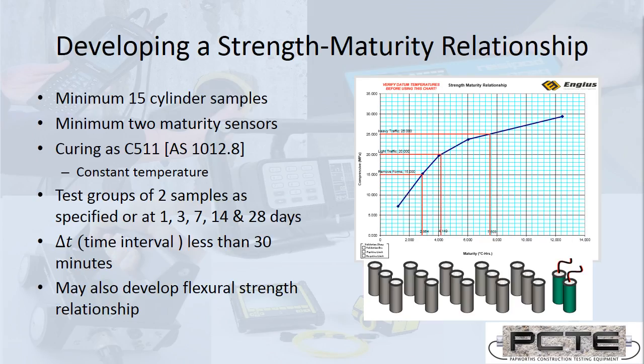So when we want to build a strength relationship, it's a large-scale batch test mix. So we build maturity relationships for each type of concrete to be used. We will cast a large number of cylinders, at least 15, and we're going to embed our maturity sensors, which are logging the time history of the concrete, and they may be calculating one of the maturity indexes as well. And we are then going to break these cylinders at intervals.